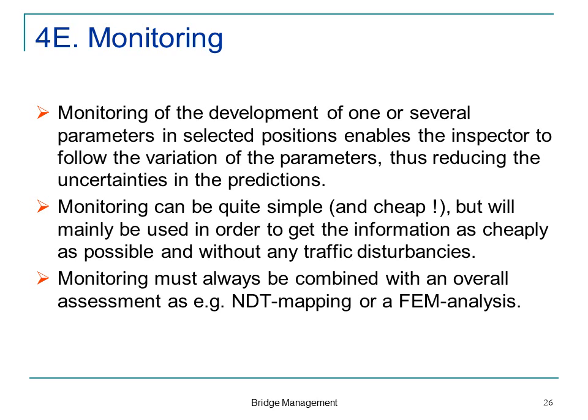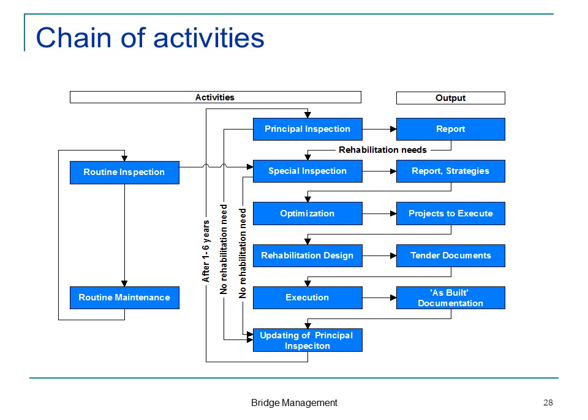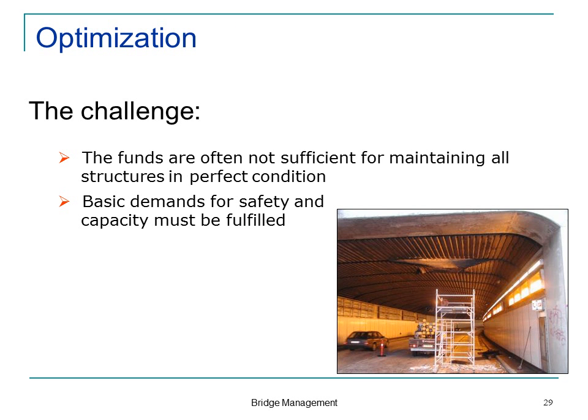a specific point, or 10 specific points, which means you follow these points in great detail. But because of that, you must always combine it with something else, like a mapping of the corrosion activity. If you have a map saying this large area of corrosion was like this on this date, then you insert sensors in pre-selected spots, and you follow how it develops in time in these spots. But you need to combine it.